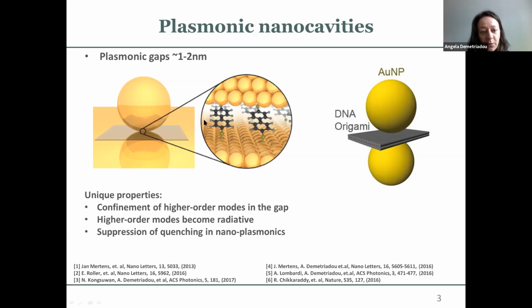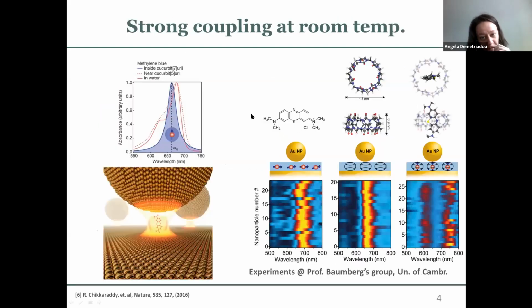Well, by having such a small gap, you confine your fields, and the hotspot that you're creating is a lot stronger. You confine even higher order modes, that it's a lot more difficult to confine if you have a gap of 5 nanometers or 10 nanometers. And by confining those higher order modes, they start becoming radiative. So instead of being dark and absorbing energy, they actually emit to the far field. And a reason that we also highlighted 3-4 years ago is that with these cavities, you can suppress quenching. And I'll talk a little bit about that.